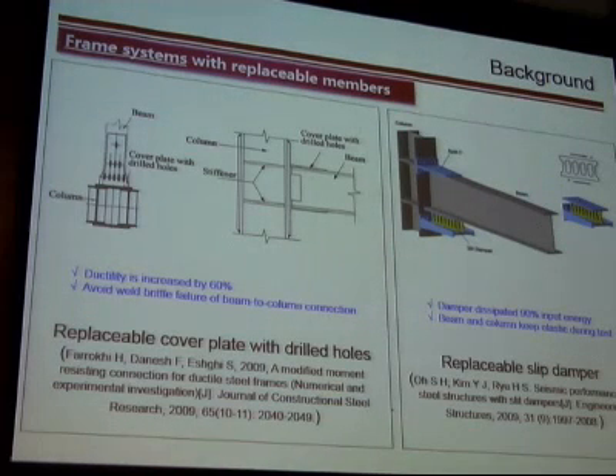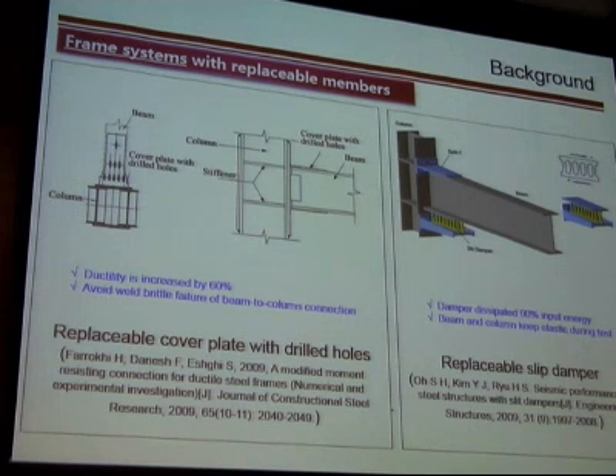And next is the frame system with replaceable members. On the left is a replaceable cover plate with drilled holes, and it's a steel frame. The cover plate with drilled holes can avoid the weld brittle failure of beam to column connections, and research also shows that ductility is increased by 60%. And on the right is also a beam to column connection, and it's a replaceable slip damper, and the slip damper could dissipate 90% of input energy, and the beam to column keeps elastic during the test.